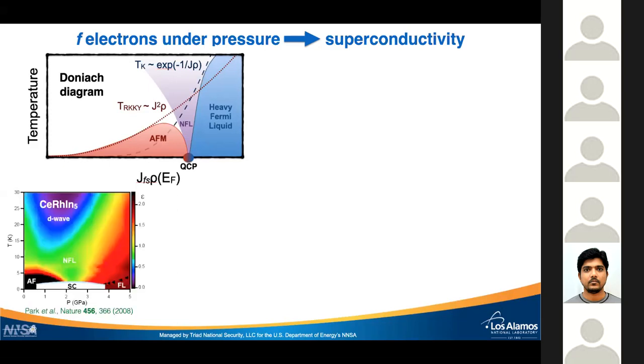And in fact, that is the case in many F-electron materials. Here is a prototypical example discovered at Los Alamos, CeRhIn5. We can see here the temperature-pressure phase diagram. Again, at low pressures, the system orders magnetically. Under pressure, the hybridization increases, or the coupling J increases. And this material is driven towards a quantum critical point around which d-wave superconductivity emerges.